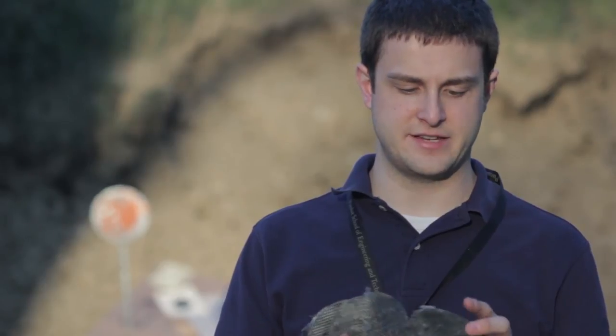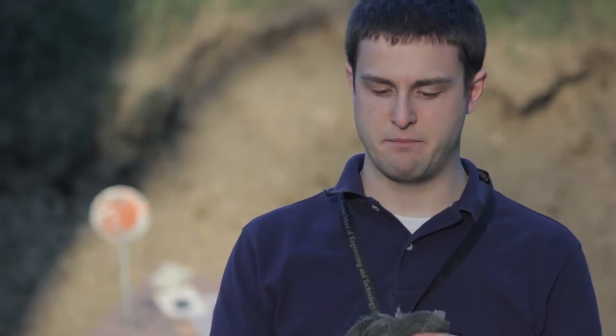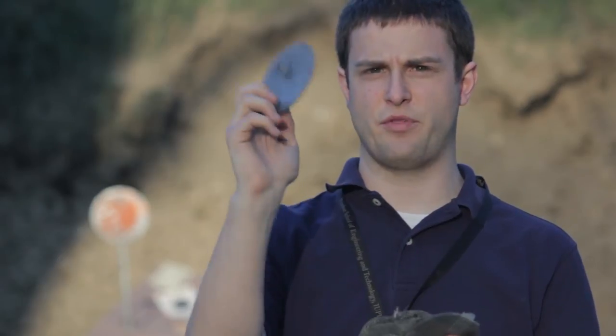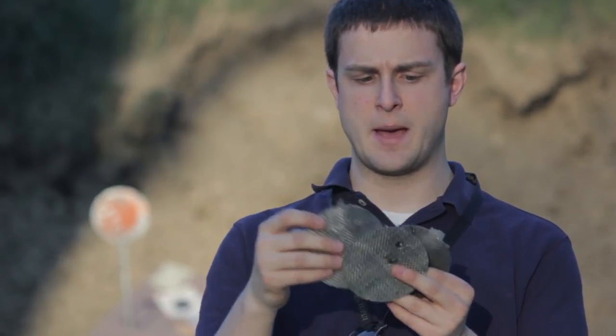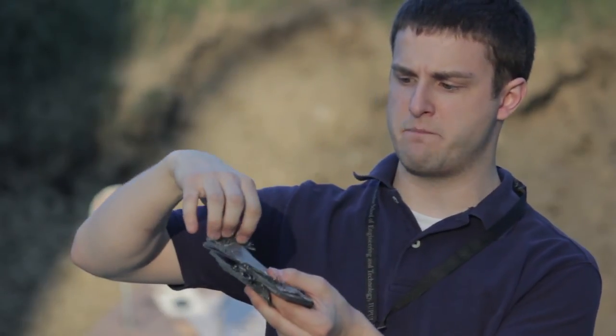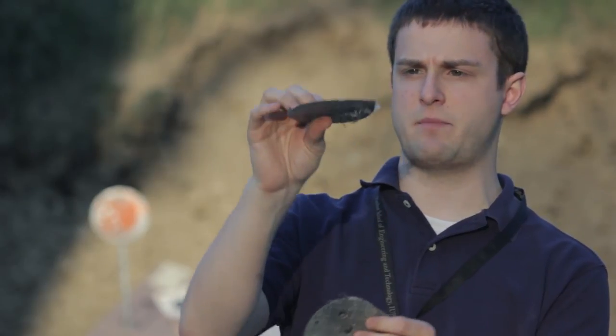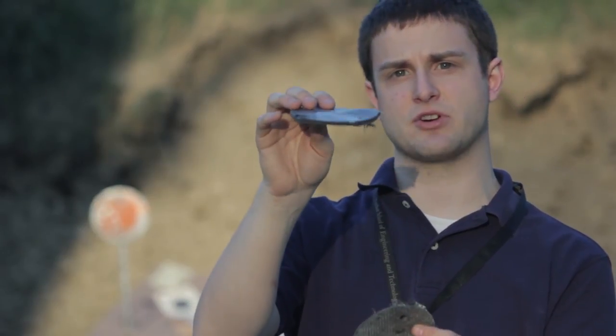We shot the Tegris puck with a .45 — this is actually a Speer Gold Dot personal protection round, hollow point. It didn't penetrate, but it delaminated in three pieces. It went through the first layer and almost punctured through the second layer, ripping it pretty good on the back side. The third layer it delaminated bent it pretty bad, but it did not penetrate.